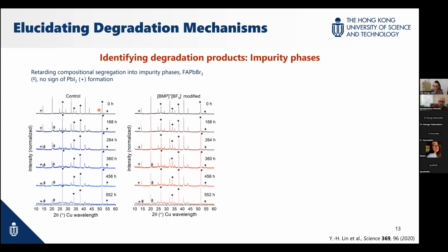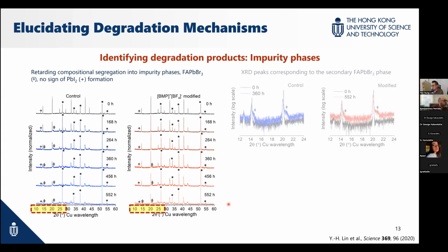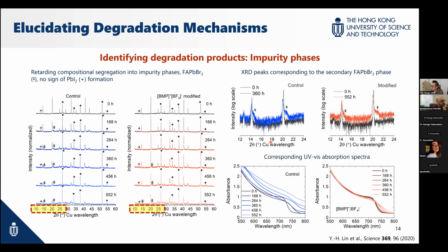So what we did, we prepared 2 different perovskite films, one control and one modified, and we aged these films in exactly the same conditions as our cells, the ones you just saw. What you can see here is that something very different happens at the smaller angle when we carry out X-ray diffraction patterns. So what we found is that the degradation product is actually different phase formations. Although it's very small, it exists in the film, especially when we look at the angle between 10 to 20 degrees. And what we found is the formation of FAPbBr3.